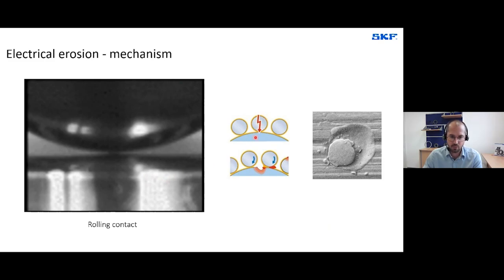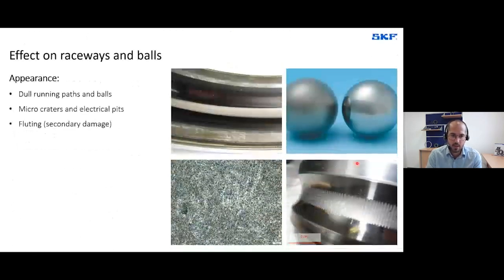And if those sparks happen in the rolling contact, it is possible that material is torn out of the surfaces, or that the material is locally molten and remolten, changing material properties. And this is leading to electrical pits, electrical erosion. Electrical erosion is sometimes very easy to recognize, in extreme cases at least, where you can see dull running paths on raceways and dull balls, for example. But of course, also roller bearings, by the way. If you look at those rings which are subjected to electrical erosion with a microscope or with a scanning electron microscope, you can see micro craters and electrical pits very easily.